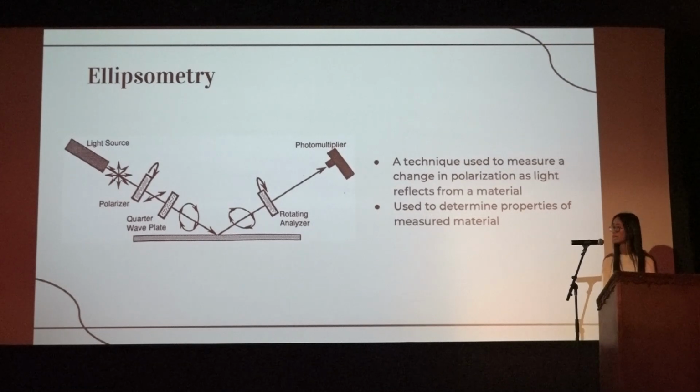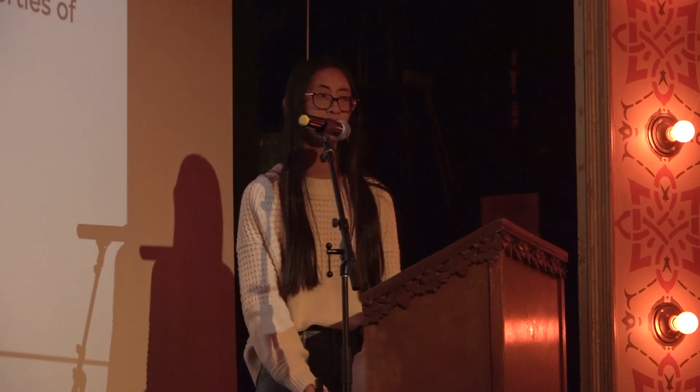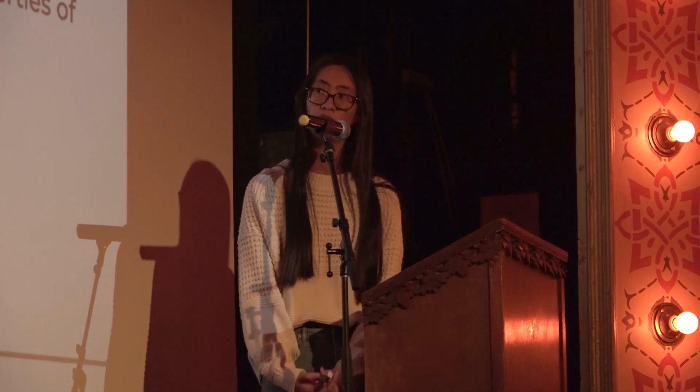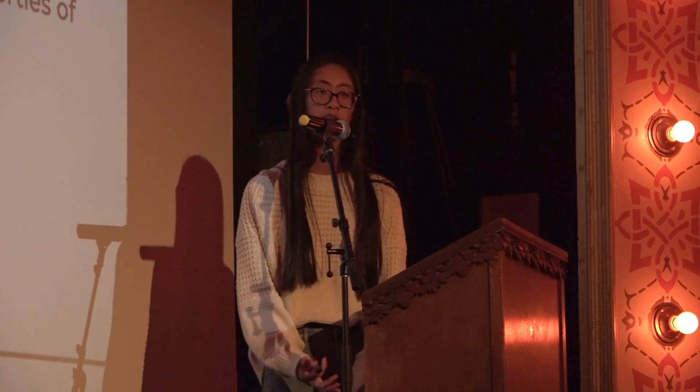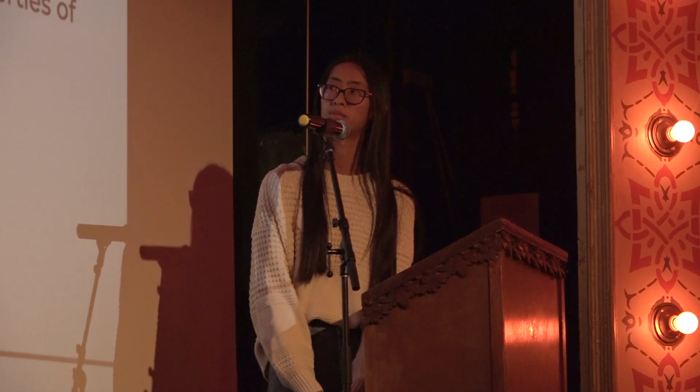It's a technique used to analyze the change in polarization, which is then used to calculate certain properties of measured materials. So certain things like thickness of very, very thin films or surfaces on a very microscopic level. And so my project was almost like a part two of another intern here, Seda, where she made very thin films and my job was to analyze for the thickness of it. So we're talking like 10, 20 nanometers using this technique called ellipsometry.